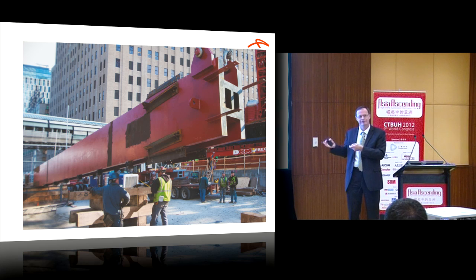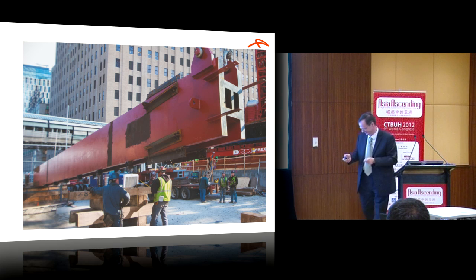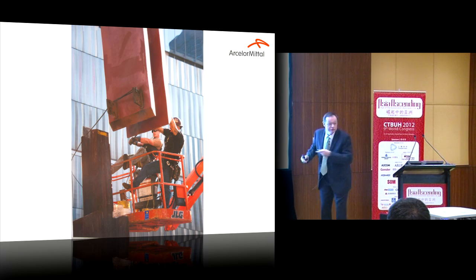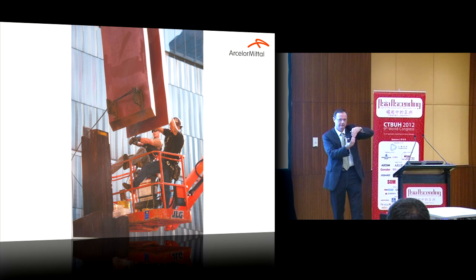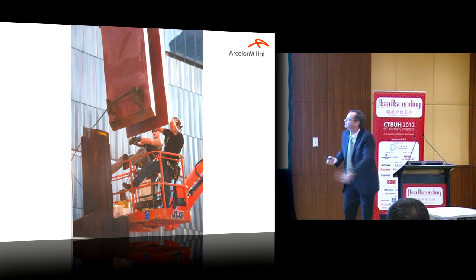I asked different steel fabricators in China, and they say, oh, less than one day we do it. On top, when you splice all this column, don't put all the welds in one plane, because if something happens to the weld, the crack will go through one plane. So in the Freedom Tower, for example, when they are splicing the jumbos with the plates, they put the weld of the plates here, and they are welding the jumbos here. So they put the welds at two different locations to have a much safer structure.